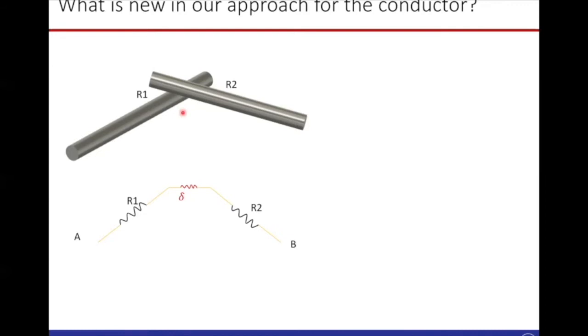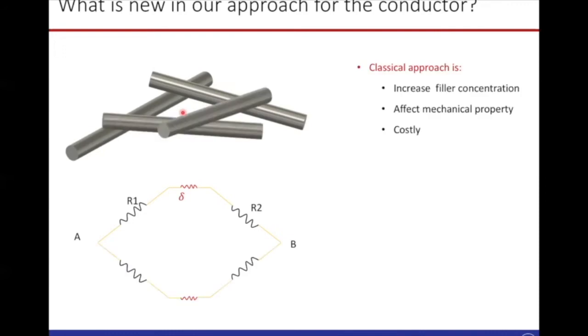Especially at a lower filler concentration. So people adopt this method. The classical approach is to increase the filler concentration. As you increase the filler concentration, you open a new electrical network, and thus you open a new path for the electron flow. But increasing filler concentration could affect the mechanical property of the polymer, and it will be costly because the nanomaterial is very costly.